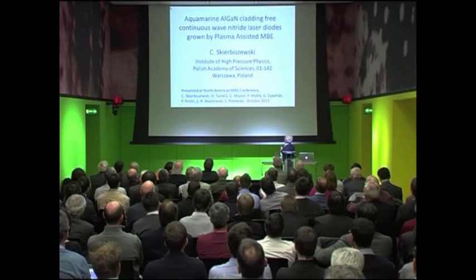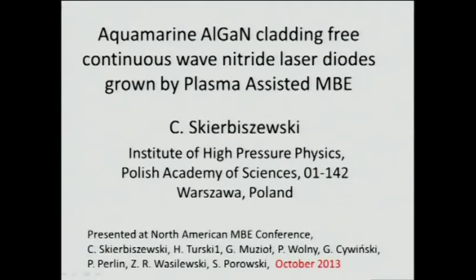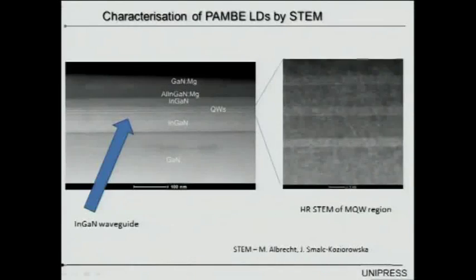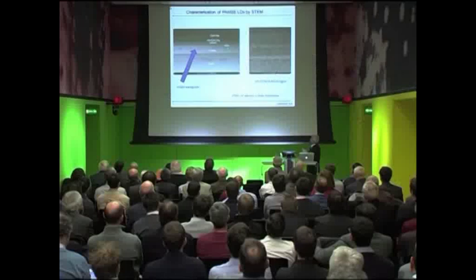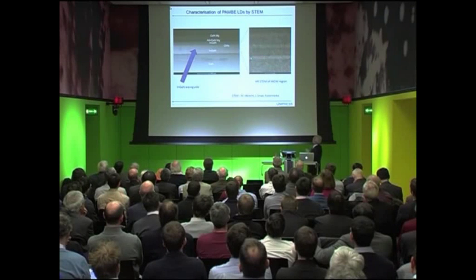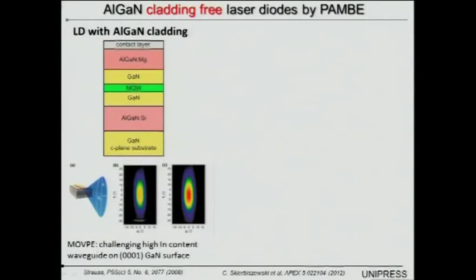Extremely outstanding work. He showed aluminum gallium nitride cladding-free continuous wave operation of gallium nitride lasers by plasma-assisted MBE system. He showed the schematic and the photomicrograph; look at the precise, uniform, good interface of the quantum well structures grown by MBE for these nitride lasers.